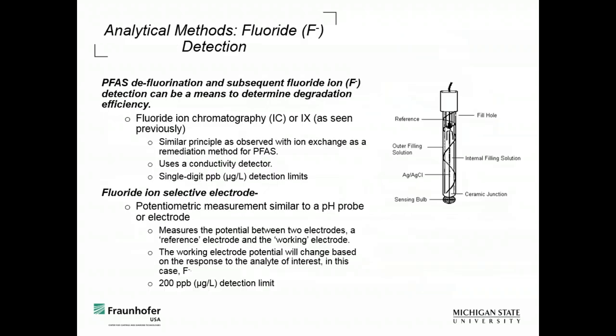Another thing we can do is, since we do defluorination, we can use fluoride ion selective electrodes at higher concentrations as a way to indirectly monitor our PFAS degradation. So we did this for a few of the figures that I'm going to show, because it's $900 for one ISE probe that we can use for a few months before you have to buy a new one, but that's still a little bit more cost effective. The downside is that we don't get this extra layer of information about maybe the mechanism and what sort of PFAS we might be making in solution based on our degradation processes.